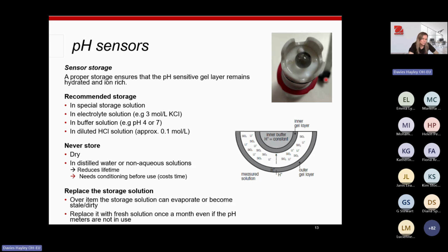You can use that, or you can just use an electrolyte solution, 3 molar KCl. That is the electrolyte used in a lot of the pH electrodes. You can make up your own solutions of 3 molar KCl. If you don't have any 3 molar KCl, you can store it in a buffer solution, so you can use a pH 4 or a pH 7 and store your pH probe in those. Or in a diluted HCl solution, hydrochloric, so about 0.1 molar. Any of those you can store your electrodes in.